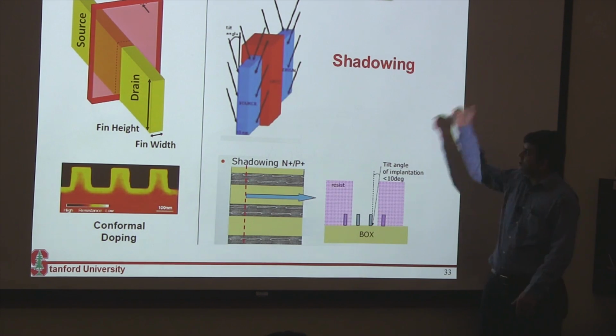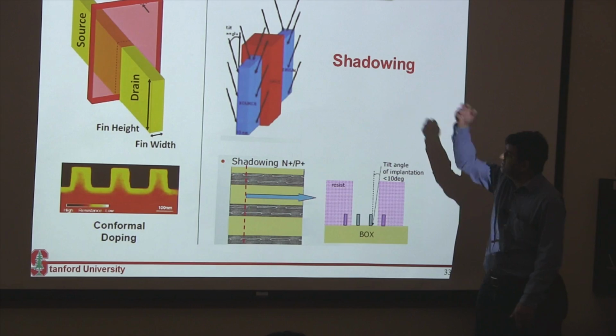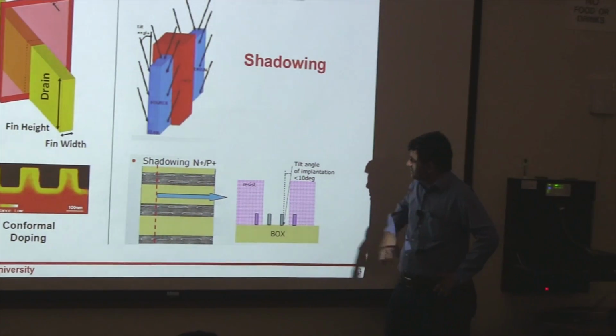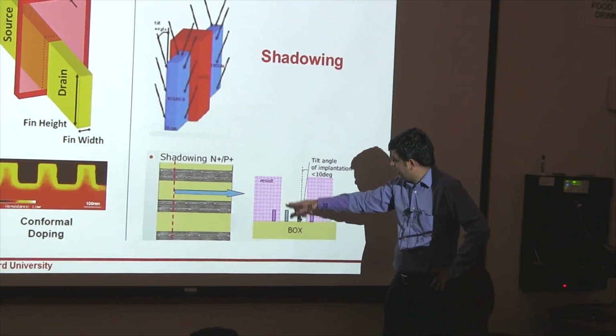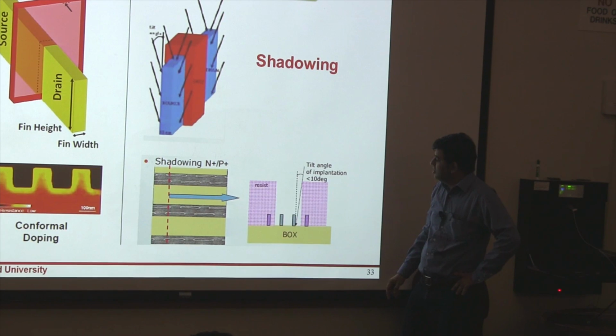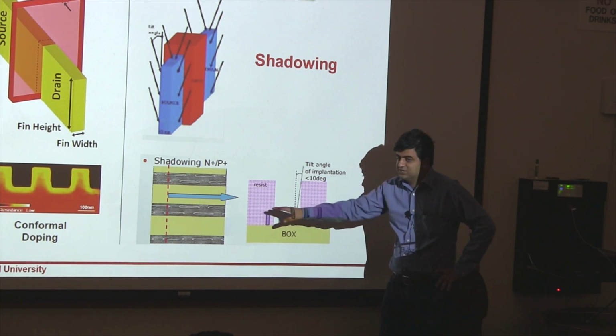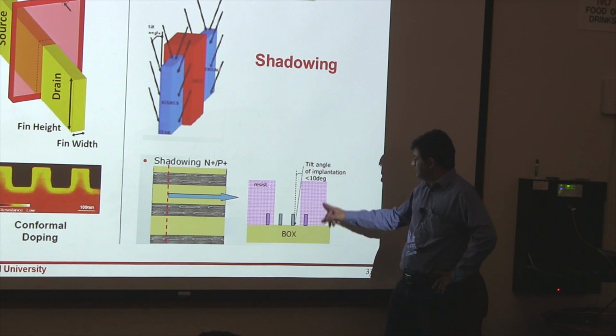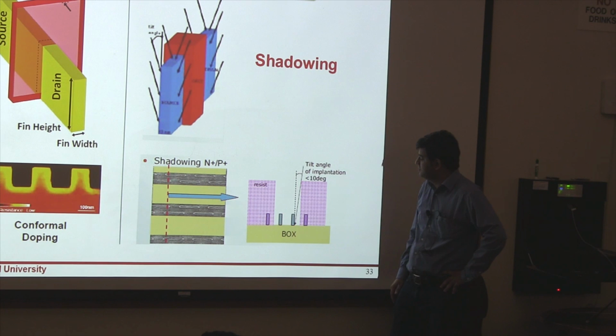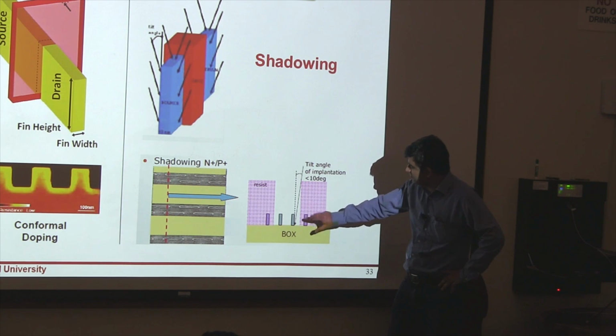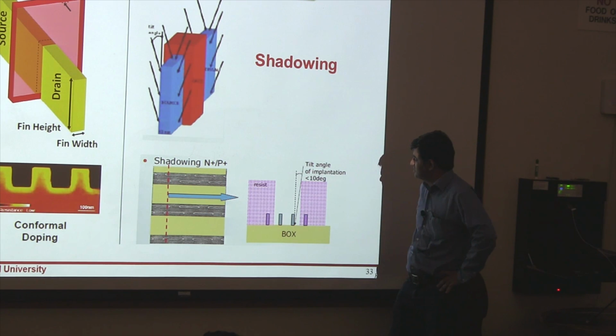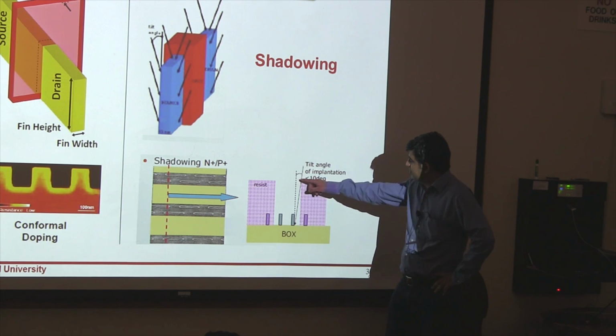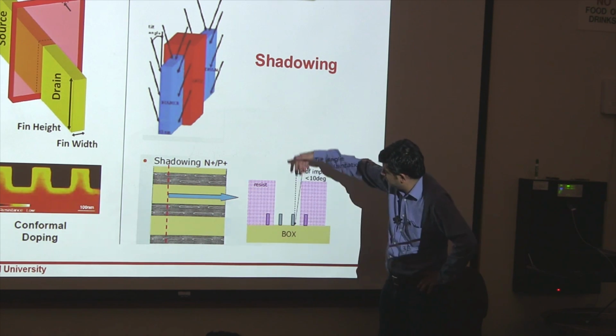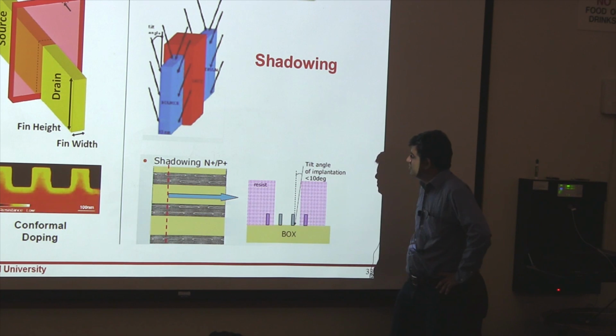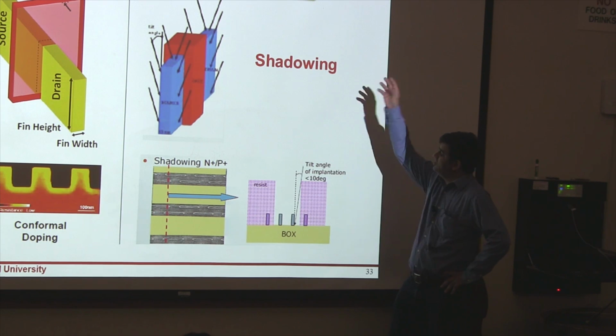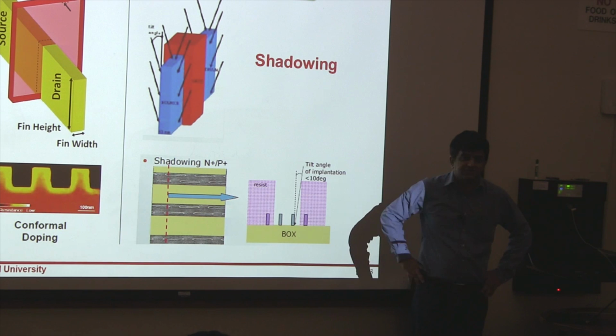So what you need is really all these implants happening at different angles. And the problem with that is, since these fins are 3D and they're hanging out of the surface, when you want to implant your P fins, you want to probably protect your fins, which are your NMOS, and you have this photoresist which will have a certain thickness too, and that photoresist at least has to be thick enough to cover these fins, right? Otherwise it won't protect these fins. So whenever you do that, you are restricted by the amount of tilt that you can get into this window, because you have this very narrow window into which you want to do your implant. So again, forming your junction becomes much more complex when you have this 3D device.